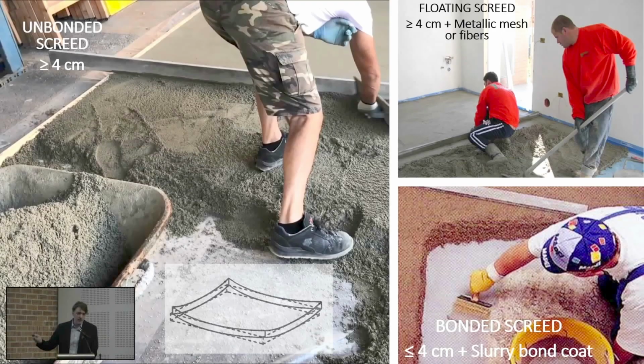So if you do 3 centimeters of cement, but you don't fix it with the slurry bond coat, it will lift up on the corner and will be broken. And once the screed is broken, the tile will be broken. Okay, so now we don't go through all of them. Here there is plastic, you see. Here there is a flexible material under the screed, a thermal isolation panel. So every one of them has some specific requirement to be respected.